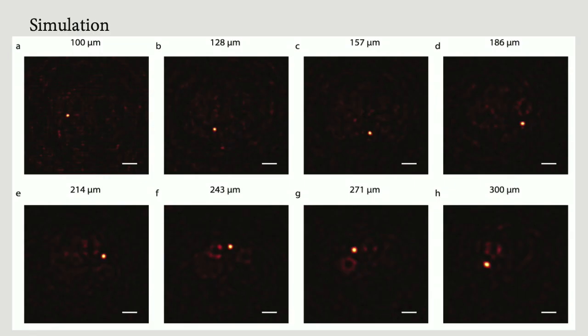So this is how our simulation looks. The light is going to focus at different spots. If you look closely, you can see this dark spot that we tried to make in the neighboring plane. This XY location is here, and we want to make it a dark spot, and this is along the optical axis. Now we want to test it, but it works only for spheres, right? How do you fabricate a sphere? Spheres you cannot make with e-beam lithography. So we used 3D printing.